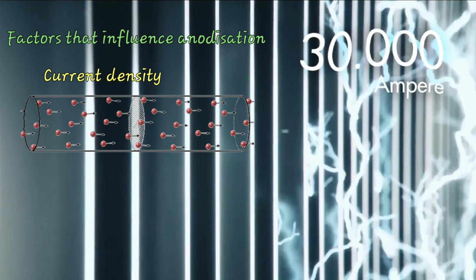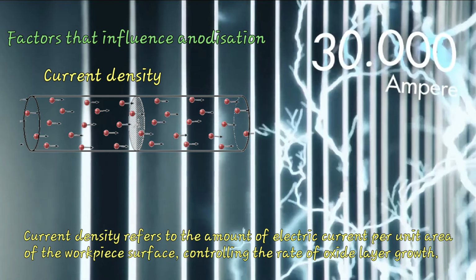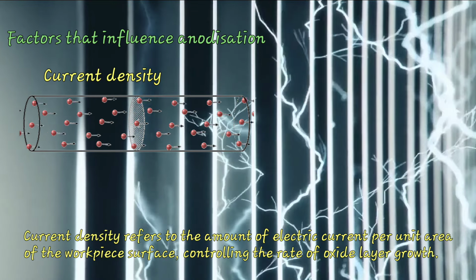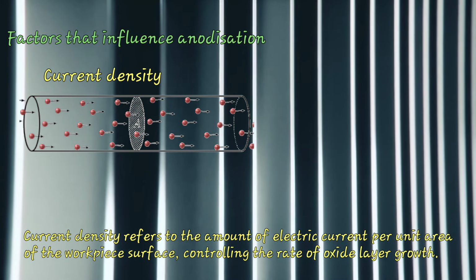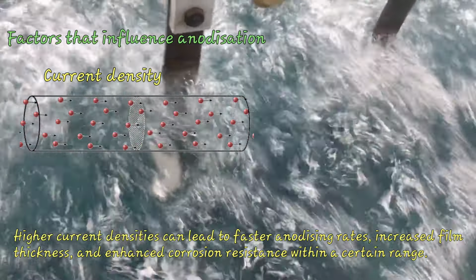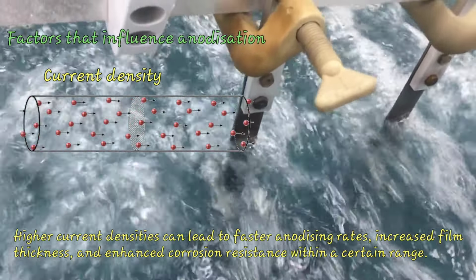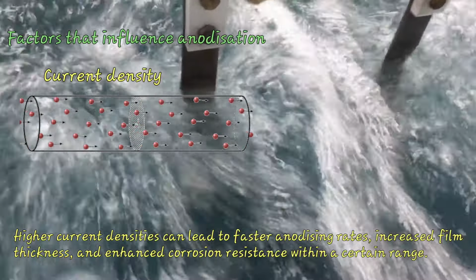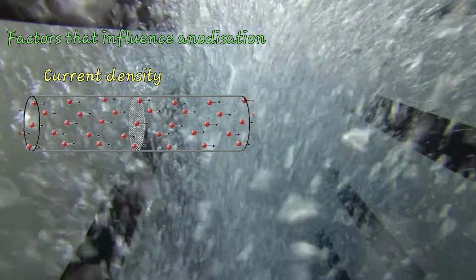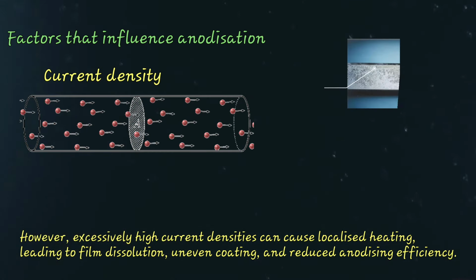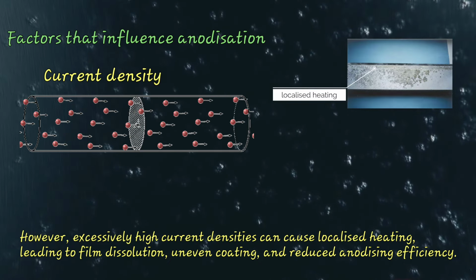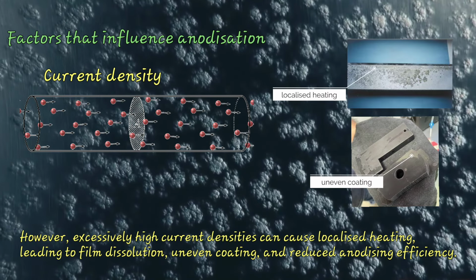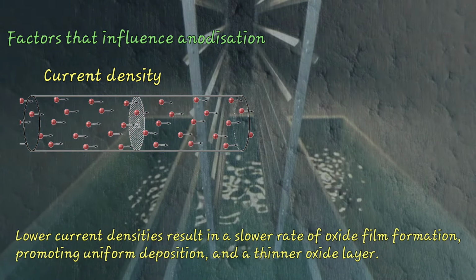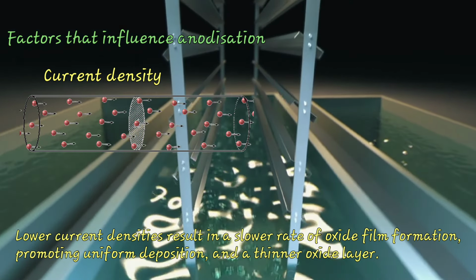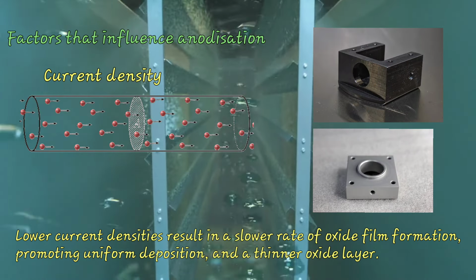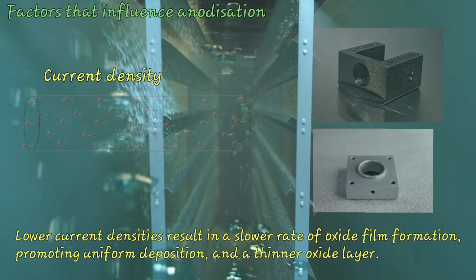Current density. Current density refers to the amount of electric current per unit area of the workpiece surface, controlling the rate of oxide layer growth. Higher current densities can lead to faster anodizing rates, increased film thickness, and enhanced corrosion resistance within a certain range. However, excessively high current densities can cause localized heating, leading to film dissolution, uneven coating, and reduced anodizing efficiency. Lower current densities result in a slower rate of oxide film formation, promoting uniform deposition and a thinner oxide layer.